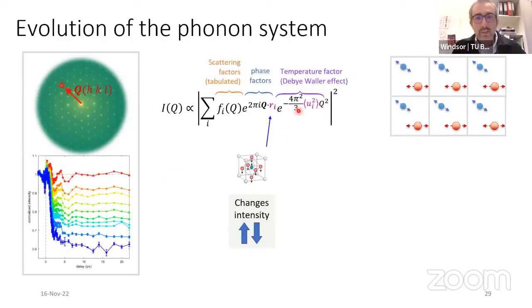Now, energy flowing to the lattice doesn't necessarily need to lead to coherent phonons. Most of the energy produces incoherent vibrations of atoms like this, which reduce intensity. As you see, if you just have a growth in how much this atom moves around, you will have a growth in this temperature factor and therefore a reduction in intensity, which is what we see here. And because of this Q squared term, the atoms that are further away from the center reduce more. It's a Q squared inside of an exponent with a minus. It's very intuitive.